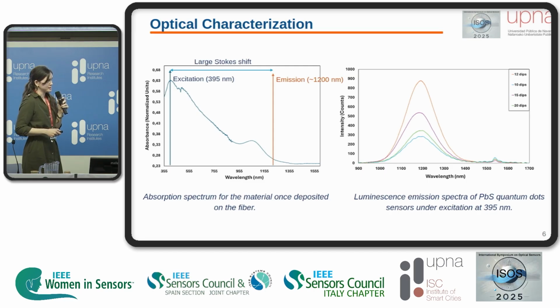As we can see in the slide, here is the luminescence emission response for the sensors with 10 dips, 12, 15, and 20 dips. For the temperature calibrations, we discard the sensor with 10 dips because of their low emission.